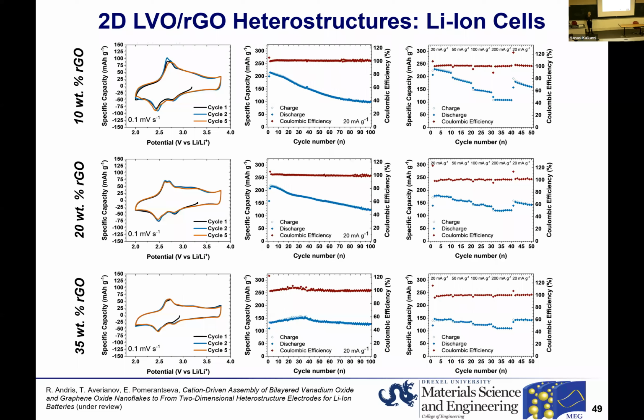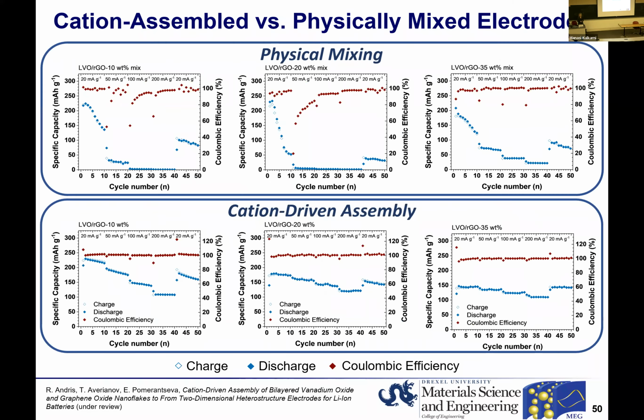So now we work on developing this further to better understand the fabrication process, and we want to minimize the amount of graphene oxide. And that requires us to exfoliate bilayered vanadium oxide better, maybe use other solvents, and there are multiple parameters that can be changed. But to me, this is a very exciting result, because it does show that bilayered vanadium oxide can be stabilized through the two-dimensional heterointerface formation.